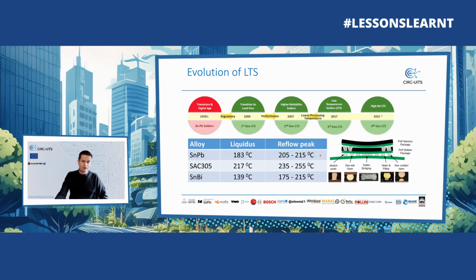And the alternative when the ban on lead came was a SAC 305 alloy, and this is a tin silver copper alloy. But because of the copper in there, the liquidus temperature was quite higher compared to the lead alloy, being at 217 degrees C. So that meant we had to increase the reflow temperature. With the increase of the reflow temperature, there came a strain on both the PCB as well as on the package, and that introduced the risk of warping. And warping causes various soldering defects such as non-wet open, solder bridging.